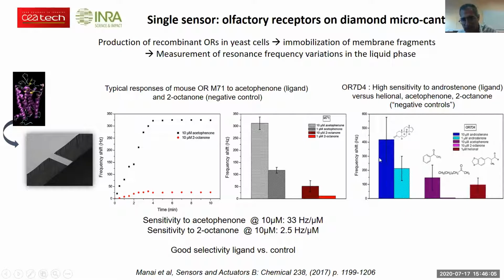So we are getting similar results. Again, some very nice selectivity, for instance, with the mouse olfactory receptor M71, which is known to have a high affinity with acetophenone and not so much with 2-octanone. And indeed, we can see that our sensor is very selective to acetophenone.